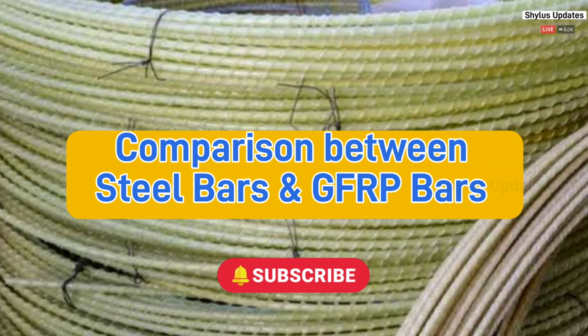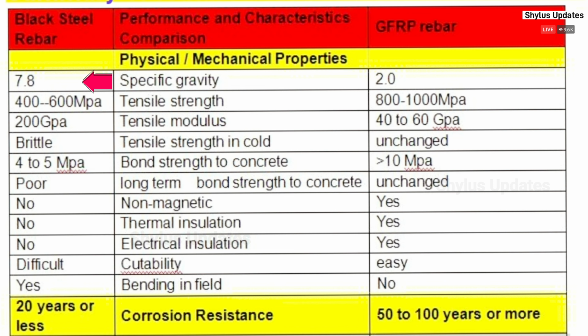Comparison between steel bars and GFRP bars. Specific gravity of steel bar is 7.8. Specific gravity of GFRP bar is 2.0. Tensile strength of steel bar is 400 to 600 MPa. Tensile strength of GFRP bar is 800 to 1000 MPa. Tensile modulus of steel bar is 200 GPa. Tensile modulus of GFRP bar is 40 to 60 GPa.